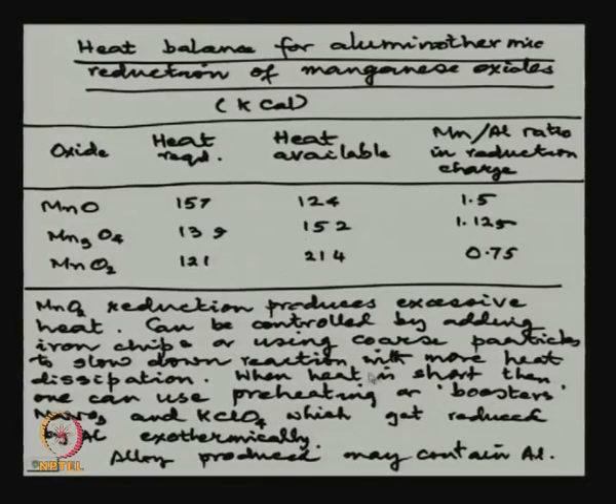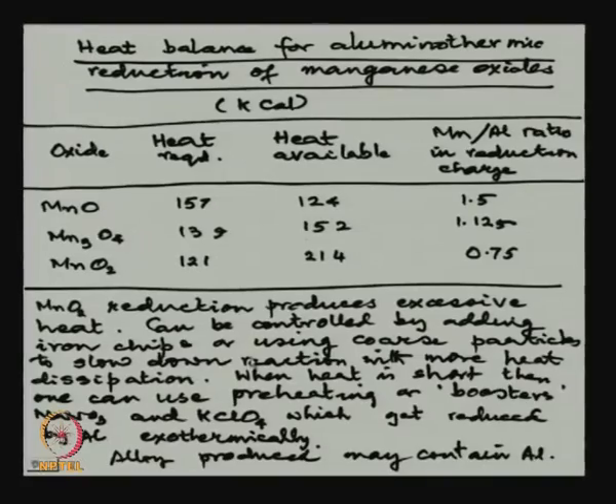On the other hand, when heat is short, like in this case where heat available is less than heat required, we can help the charge by what we call a booster reaction. Like if we add some sodium nitrate or potassium chlorate, they will get reduced by aluminum exothermically, and there is no harm done, because what will remain, KCl, will go into the slag and heat up the charge. So, in the industry, if you want to apply aluminothermic reduction for production of a metal from its oxide, all these kinds of heat balance calculations are done to see what is the right kind of charge. If there is an excess heat, it has to be absorbed.